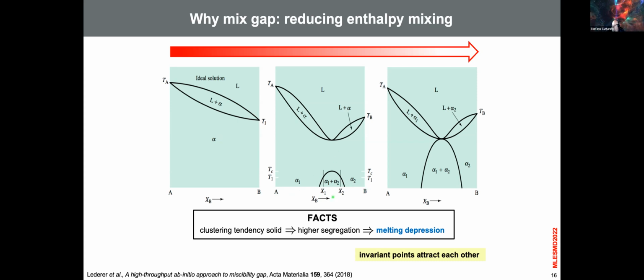Then if you decrease the temperature, you form this line here, which, as I told you before, is called the miscibility gap, all right? By the way, the gap is versus X, not versus Y. And the top here is called the critical temperature. Okay, what does it mean? It means that at low temperature, they will have a mix of A rich and B rich, and at high temperature will have a random mix, okay? But this is also associated with the decrease in the melting. This has been known for 200 years. So the clustering tendency of the solid, which means that A prefers A more than B, leads to higher segregation at low temperature and brings melting depression.